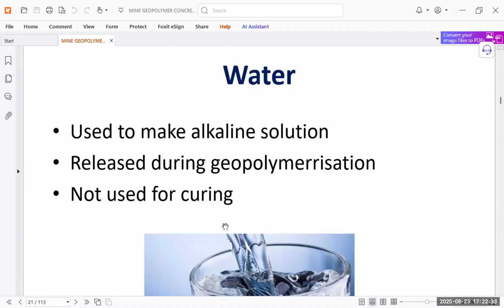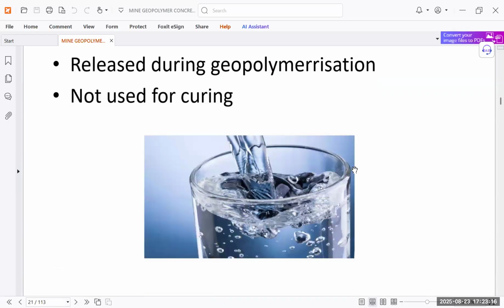You can see now geopolymer concrete is not only reducing the cement content, but it is also reducing the use of water, because curing is a very important part, as we already know. But in this, water is not used for curing, it is used just to make the alkaline solution, and it is released during geopolymerization. That is the need of the time: water should be less, and we should do less curing, because water is very scarce, especially in Delhi. In some regions, all over India, water is going down and is polluted. So that's why water requirement is reduced, and cement requirement is also reduced. That is the reason why this research on geopolymer concrete is getting focus.